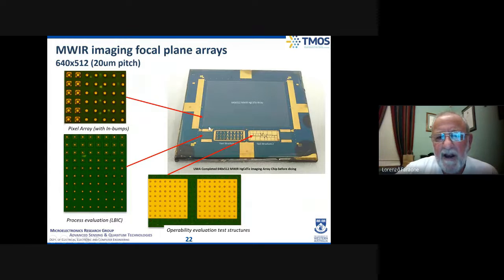Once the array is fabricated, you then need to form what I call indium bumps. Each of the 640 by 512 detectors - nearly 330,000 detectors in an area around a centimeter by a centimeter - needs indium bumps, which are simply indium balls on top of every detector, because that's what forms the electrical contact to the silicon CMOS readout circuit.